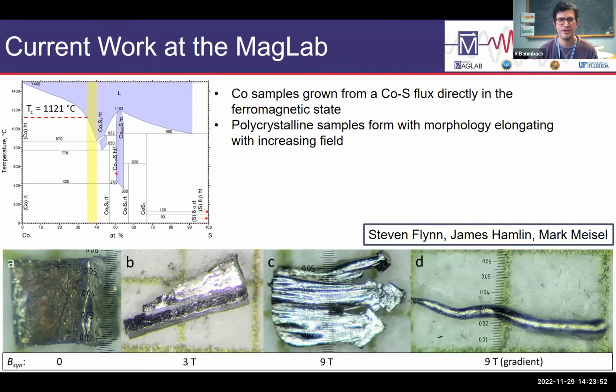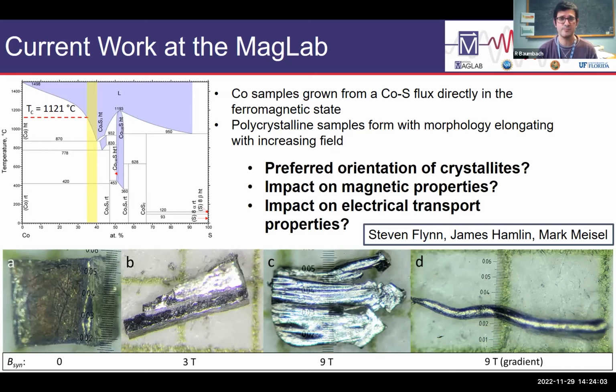That's illustrated on the bottom of this slide, where crystals grown in 0, 3, and 9 Tesla, as well as a 9 Tesla gradient field, clearly have different morphologies. So what does this mean? Is there preferred orientation of crystallites? Does it impact magnetic properties? What about electrical transport properties? We don't know.